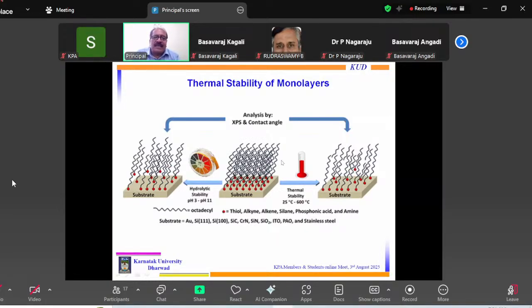What they see is, once they are created, you try to vary the conditions. pH going from 3 to 11 is a very harsh condition. pH 3 is acidic, pH 11 is highly alkaline, and even then nothing much happens, monolayers are still stable. Molecules are stable. Similarly, you can heat the material to check the thermal stability. Ranging from 25 degrees to 600 degrees, monolayers are quite stable. It means these simple materials can be put in harsh conditions and we can make electronics out of these interfaces.